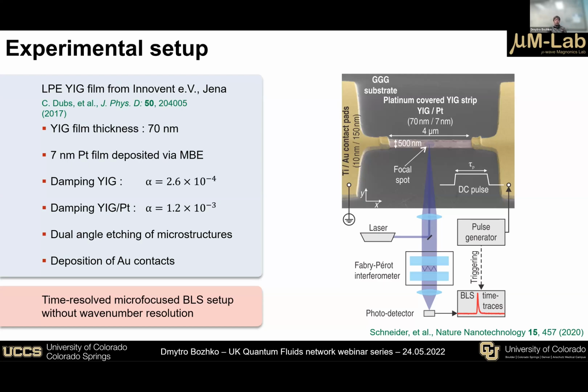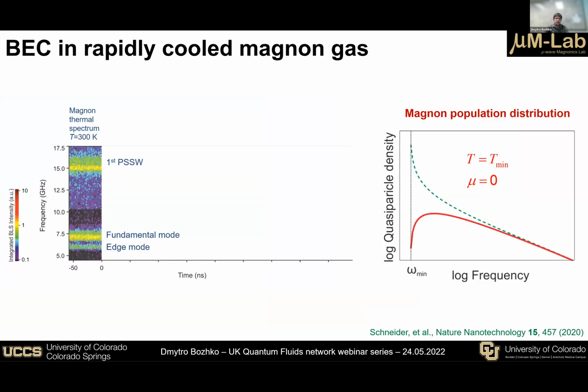So how does this cooling work? Basically, the sample is so small that the heat deposited by the titanium, gold, and platinum heater on top of the sample takes just a few nanoseconds to dissipate to the substrate. And the substrate is pretty massive. So, let's actually look at what happens with the system.